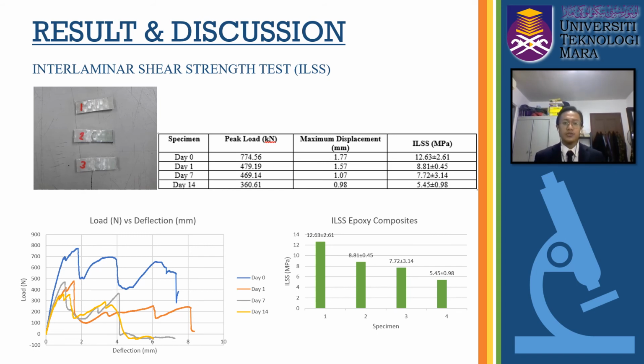The graph shows load versus deflection of the ILSS test for the specimens that were submerged in distilled water for different days. Specimen 1 had a high slope of load because there was no water absorption in the specimen, while specimen 4 had been submerged in distilled water for 14 days, which is the longest submerged time period. It is shown that specimen 4 is low in the graph compared to the other specimens. In this case, a specimen with a large amount of water absorption will have reduced strength. By referring to this, specimen 1 has better properties and produces higher ILSS properties. Thus, specimen 4 has low properties and produces lower ILSS properties.